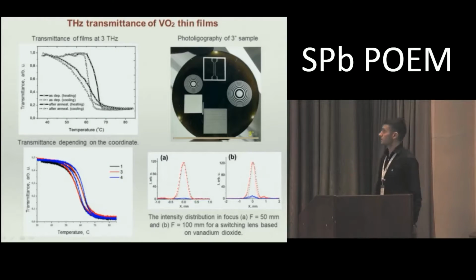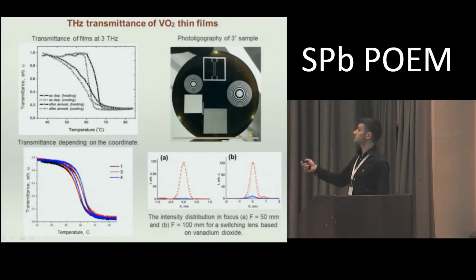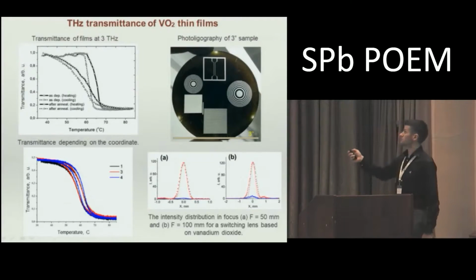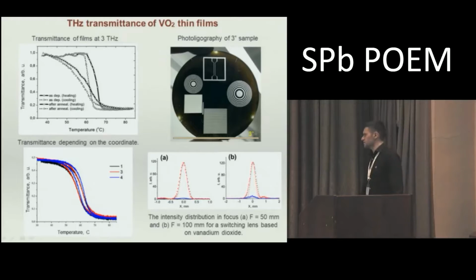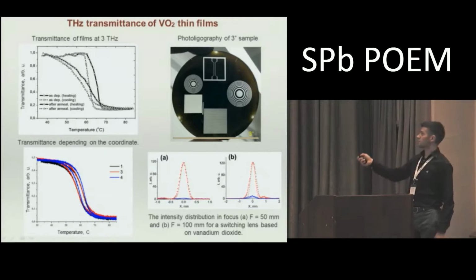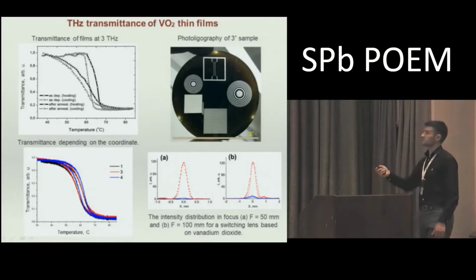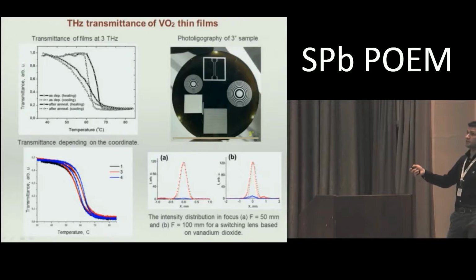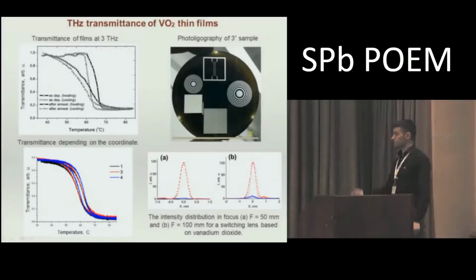Also, we made some structures on our samples. Here is a photo of our photolithography sample that we made on a 3-inch substrate. On the bottom, you see the intensity distribution in the focus for these two focusing zone plates that can be used as a switcher at the same time. In the cold state, we have focusing at 50 millimeters and 100 millimeters for these two lenses. And in the hot state, we have no signal.